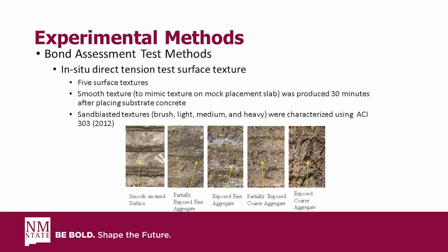Okay, so for this study, we're wanting to describe the substrate surface preparation, or what surface preparation we need. In doing so, we wanted to look at the substrate surface moisture condition as well as the substrate surface texture. First off, we'll go over the surface textures that we use in this study. We have 5 surface textures, with the first shown in the first left image, which is what we define as a smooth texture. You do see some tines in there, but the tines don't really provide enough strength for bonding or developing direct tension strength.